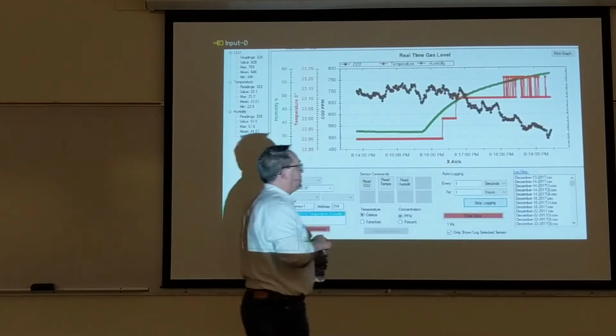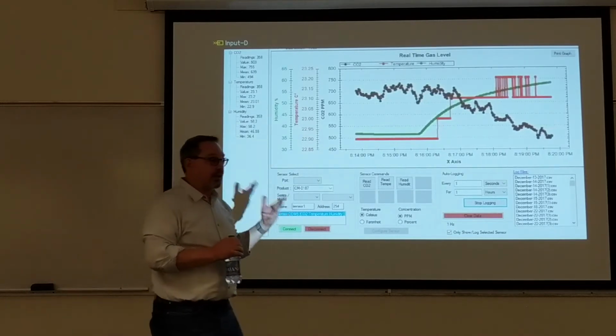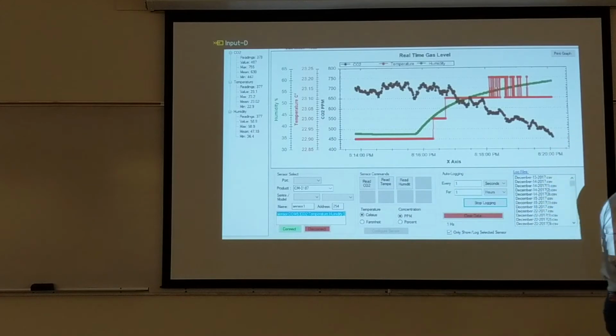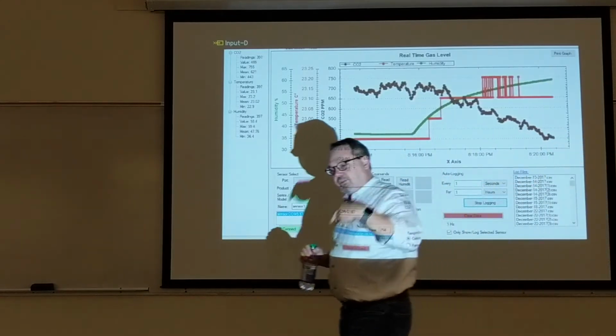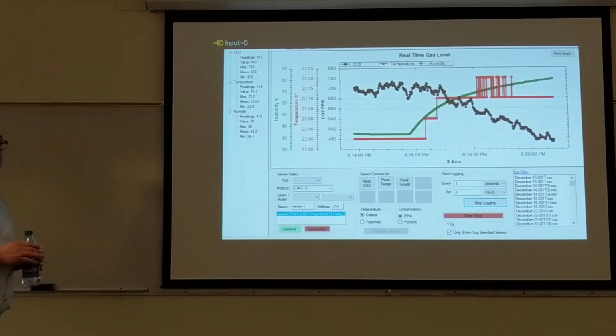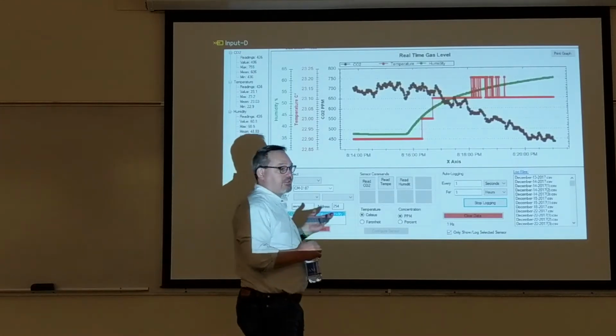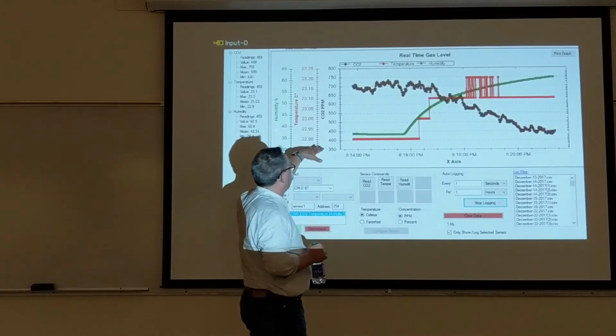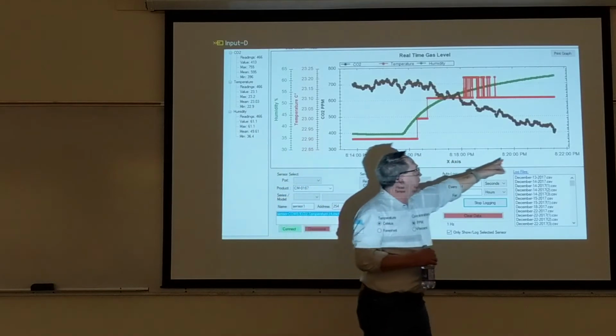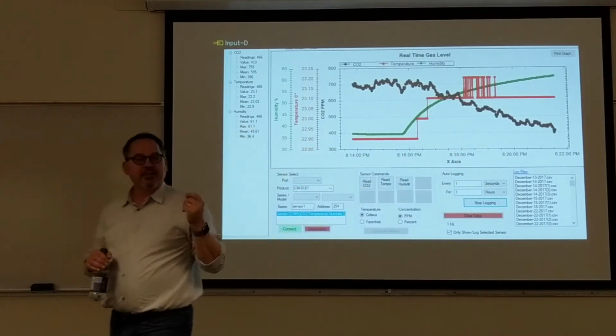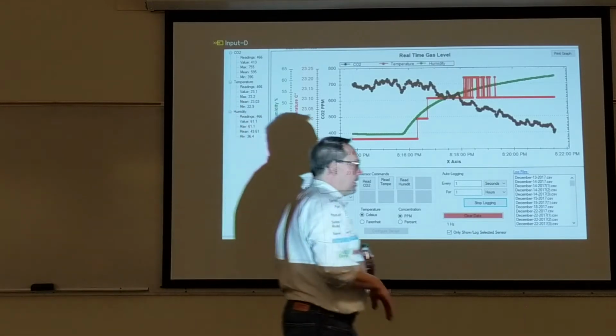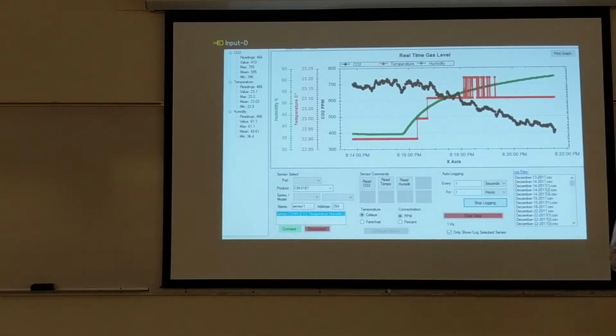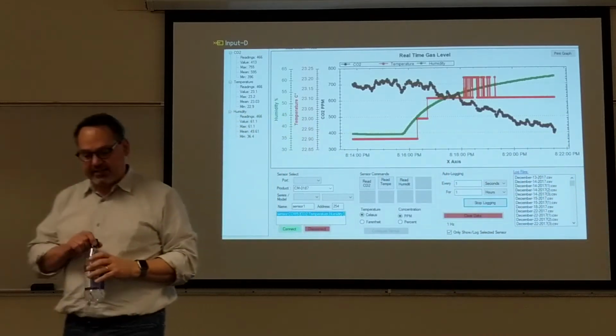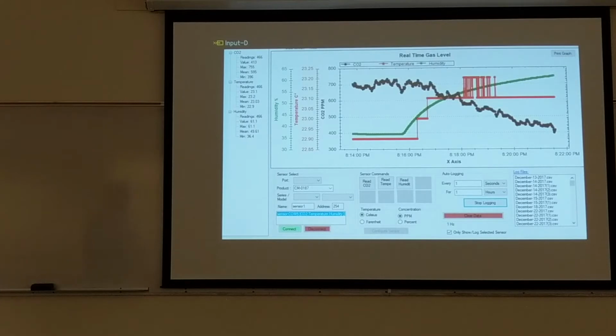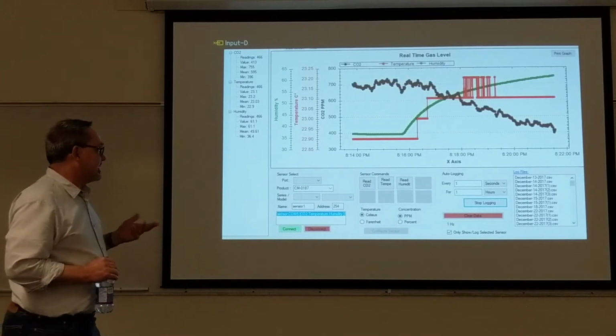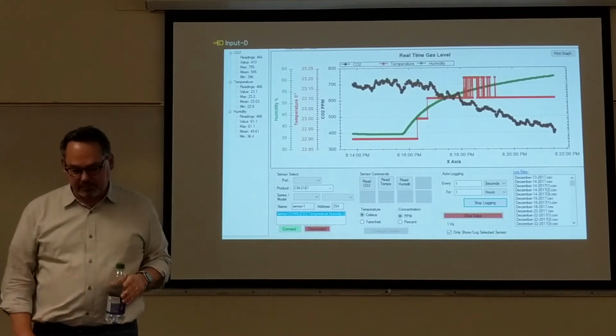As we give this 5 or 10 minutes, we'll see that we can extract hundreds of ppm of CO2 directly from the air in the room. So this is the tailings capturing CO2 from air. If we were to do this with flue gas, the rates accelerate about 200-fold. So we have faster capture from flue gas, say 10% CO2, untreated flue gas, versus what we can do with air. But you can see within about 5 minutes in this experiment, we've pulled half of the CO2 from the headspace of room air that was isolated over the tailings in this configuration. That's really just to emphasize that this CO2 capture happens quickly on human time scales, and it's easily reproducible literally in the room.